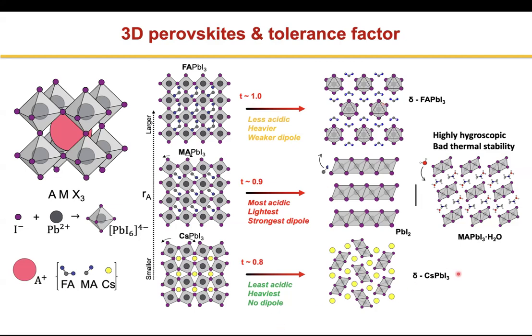Similarly, the cesium lead iodide also does the same thing because it is too small, right? And so it cannot accommodate the stresses that are involved. It's electrostatic interactions which are very strong, and so it doesn't balance the charges and gives you something which is the yellow phase. So the only thing that forms is this methylammonium lead iodide, but because methyl ammonium is very hygroscopic, it tends to degrade very quickly.